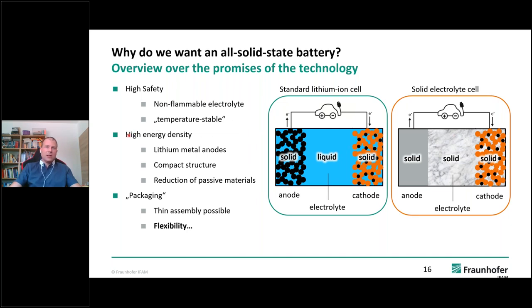And as I also said, we get high energy density by using lithium metal anodes, and maybe even compaction of the structure. Like I showed you, we have these pouch cells. We can think about different manufacturing and different appearances for the solid state battery, and also reduction of passive materials, also increasing the total energy density of our final cell, meaning that the packaging is not as big as we needed for the lithium ion cell.